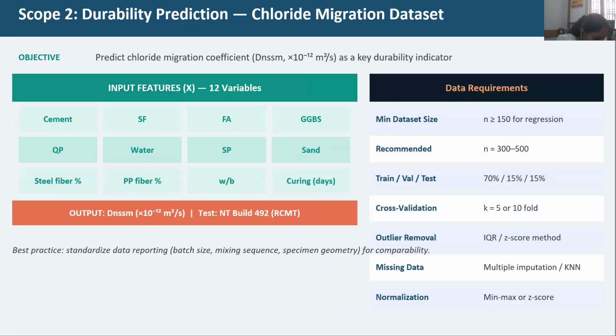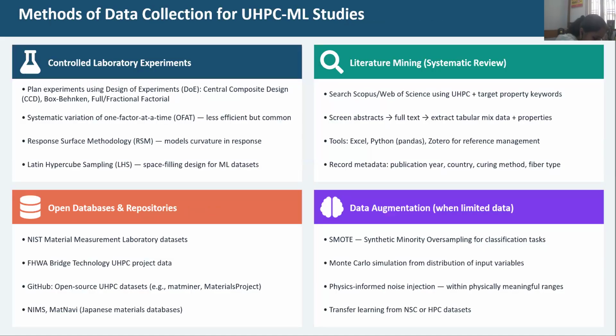The second scope is the durability prediction, where you can find out the RCPT test, that is the rapid chloride permeability test. But again, RCPT has its own limitations, so it's better to go with the rapid chloride migration test, which gives a better result. So instead of measuring just the current that is passing, you can also measure how much chloride is migrating or passing through the sample from one end of the sample to the other end. That can also be considered as one of the scopes.